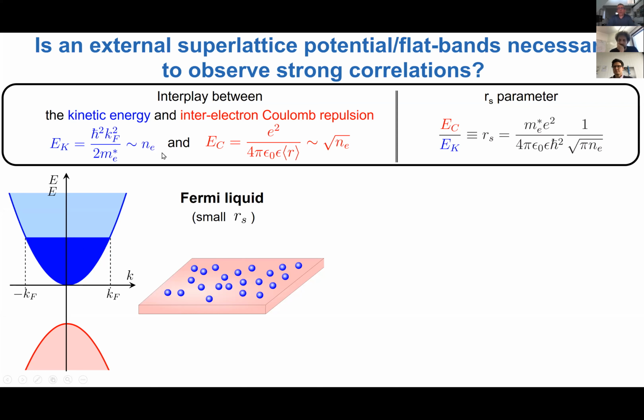The relevant energy scales would be the kinetic energy, given by the Fermi energy, which scales with the electron density, and the inter-electron Coulomb repulsion, which scales with the square root of the electron density. The ratio of these quantities, called the r_s parameter, naturally scales inversely with the square root of the electron density. It scales inversely with the dielectric screening, and it's proportional to the effective mass.